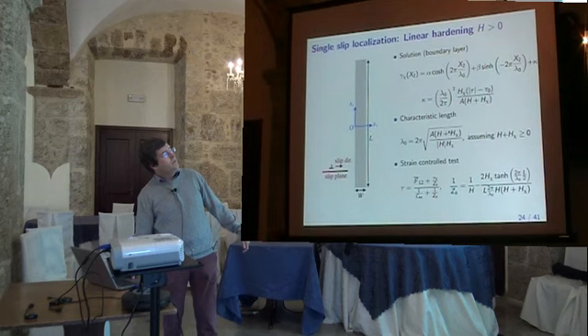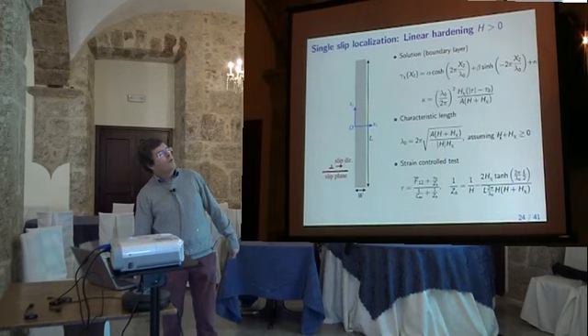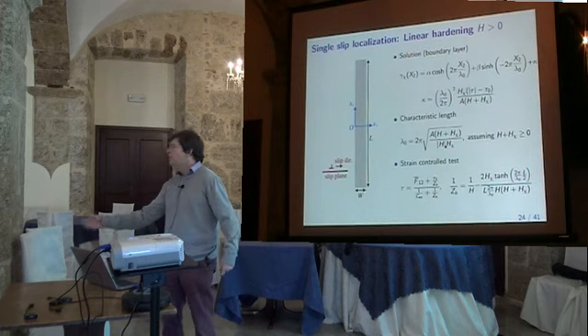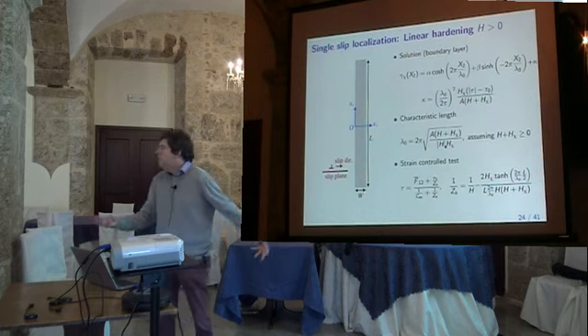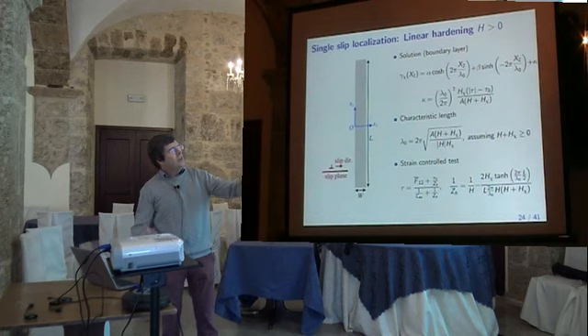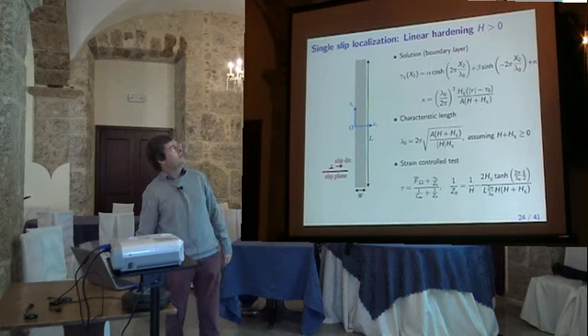in fact, simply the ratio of hardening modulus and the higher order modulus here. We assume this, of course, H can be negative, but H chi must be high enough that it's positive. I have put absolute value because I will use it later on with negative modulus, but here it's positive. And then you can, of course, solve it with a strain control. Okay, so this is a type of solution.